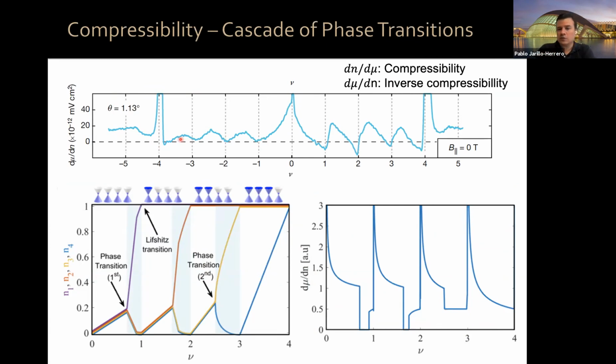Turns out this sawtooth type of behavior represents a cascade of phase transitions. A phase transition is taking place near each integer filling factor. And to 0th order, in the simplest model that we could come up with to explain this data, each of these phase transitions corresponds to a flavor polarization of the system. And I believe either Andre or Oscar will talk about this in greater detail with a more sophisticated model than the one we initially chose to explain our data.